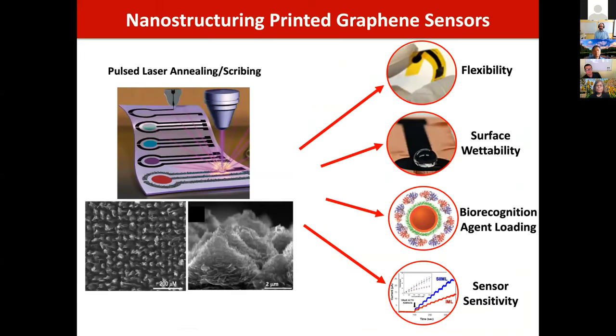So after we make that graphene surface, it's not well suited for sensors or electronics. It needs to be annealed in order to take out the binders in it, the non-conductive binders and solvents, to make it electrically conductive. But we found a way that we can anneal it, not only in a furnace, but with a laser.